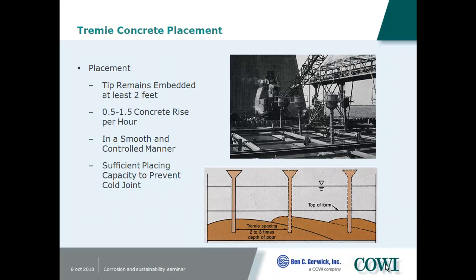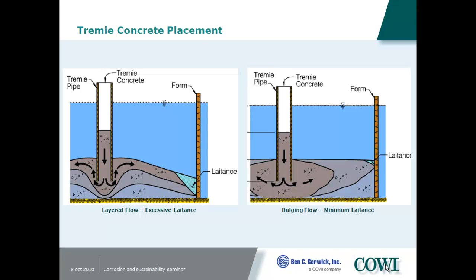You need to seal it there in the bottom to stop it from mixing with water, so you always keep the end of the pipe buried. As I said, it builds up and then flows out. If you have laitance, you want it to move all in one area so that you can remove it after the placement.